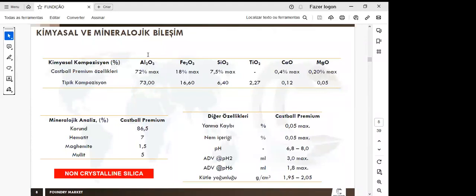Castball sand is based on sinterized bauxite, as Peter mentioned. Therefore, its composition is typical of aluminum silicate with high content of aluminum oxide. The mineralogical composition contains high level of corundum with traces of hematite, maghemite, and mullite.